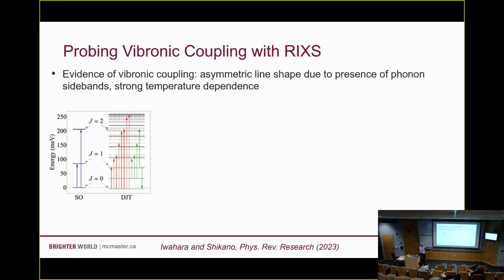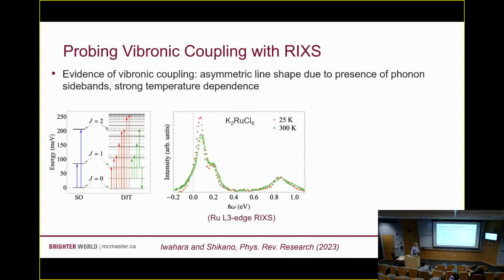one of the things that you can do by changing different edges in these resonant experiments are probe different types of excitations. And one of the things that you can use RIXS for is studying vibronic coupling. Okay, so this is an electron-phonon type coupling. And if we introduce this vibronic coupling, then you can take your regular electronic excitations that we've been focusing on so far, and you basically couple these phonon sidebands, okay, because of the strong vibrational effects that you get. So these sidebands should give you some asymmetric line shape and strong temperature dependence.